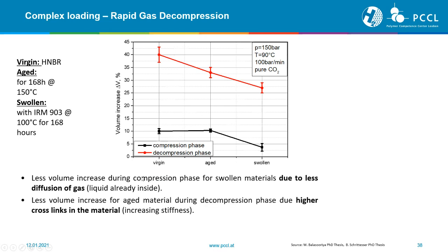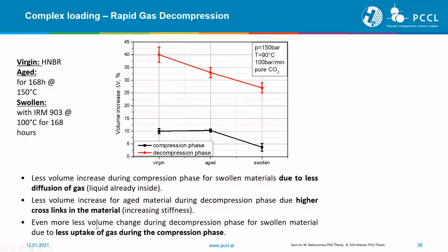When you think of our aged material from 40 to 32% volume increase, it's also clear because when you think back on the impact of thermo-oxidative aging, we've found a stiffness increase, a decrease of stress, a decrease of strain at break. And this increase in stiffness leads to a lower volume increase because this means that the material fails earlier, breaks faster, and therefore it cannot expand like a virgin one. And even more or less volume change for the swollen one, for the same reason, because we have less gas inside due to the fact that we've already some oil inside of our material.